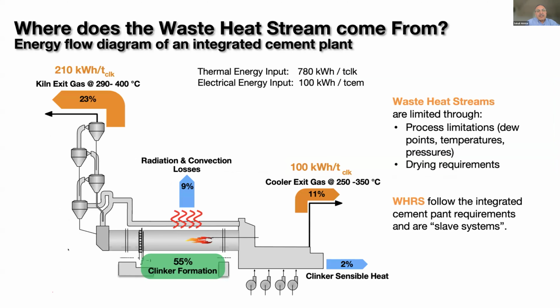So for cement manufacturing, if you look into this, this is the slide for a relatively efficient cement plant. And even here, if you look into the thermal energy input or electrical energy input, it is a significant amount of energy that goes into cement manufacturing. But the interesting thing is that only 55% of the total heat input in the cement kiln is really needed for the clinker formation, the product that we make in the cement kiln.